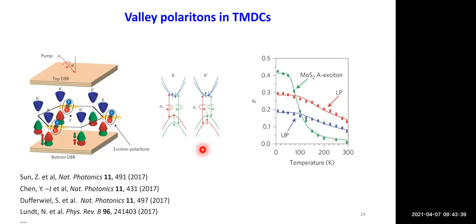And now the dynamics of these polarization-sensitive exciton-polaritons are quite distinct from the isolated valley excitons in the monolayer, and that is again because of your cavity photon component. So this represents your half of the hybrid quasi-particle, which is the photonic part, and this photonic part is basically insensitive to any of these intervalley scattering processes, which are the contributions from the matter-based depolarization process. So this kind of half-light, half-matter particle results in the preservation of the exciton-polariton valley polarization even at room temperature.